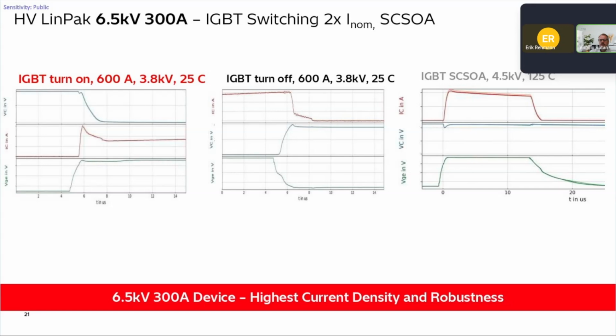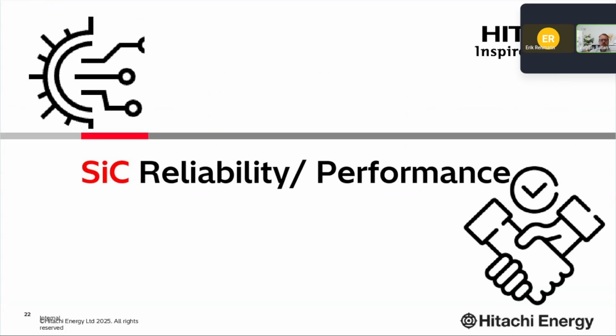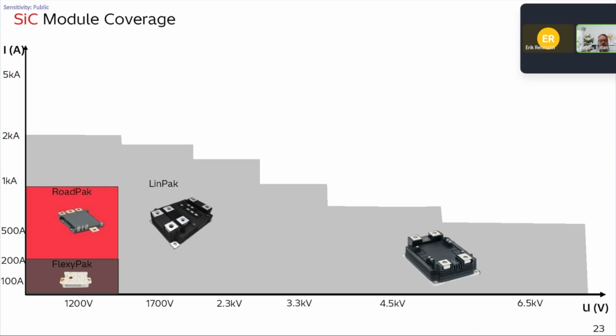So I mentioned in the beginning that we have these packages for silicon, but we can also put silicon carbide inside. What we want to cover with silicon carbide in this package is, again, in terms of voltage versus current: we have the LinPaks with the low voltage starting at 1200 volt up to 3.3, and then high voltage from 3.3 up to 6.5, also for silicon carbide.